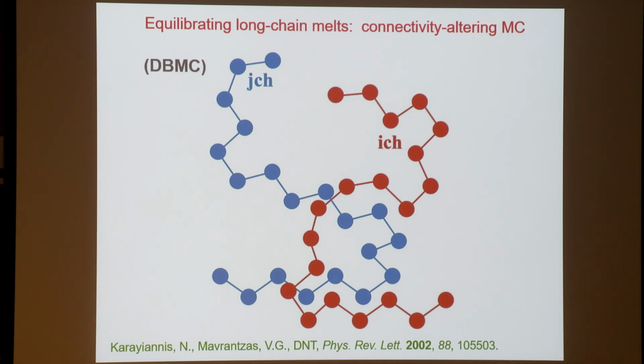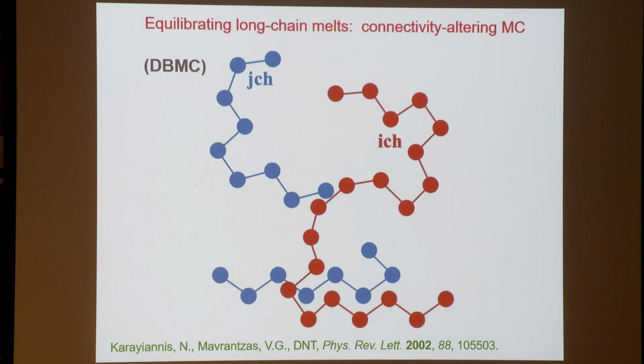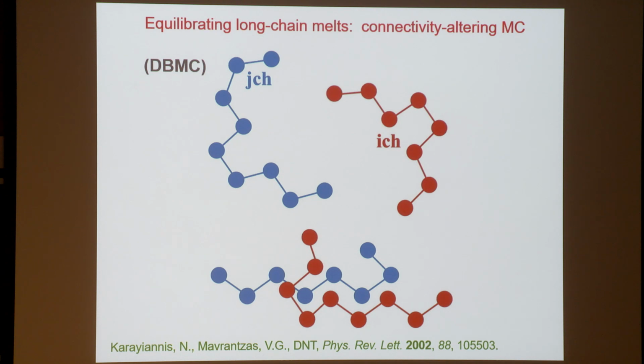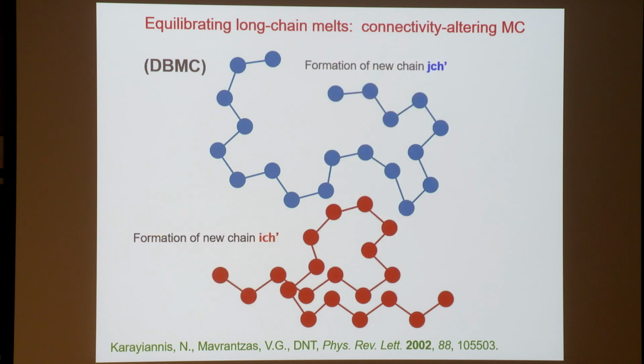For example, think of two chains running near each other in a bulk melt. One can have a move which excises a trimer segment from the blue chain and a trimer segment from the red chain, and subsequently builds two trimer bridges between the pieces that have remained, so as to give us two new chains of exactly the same molecular weight, but of very different conformation. This kind of move can rearrange the long-range conformational properties in a dense melt state very effectively, so we use it in order to equilibrate long-chain polymers.